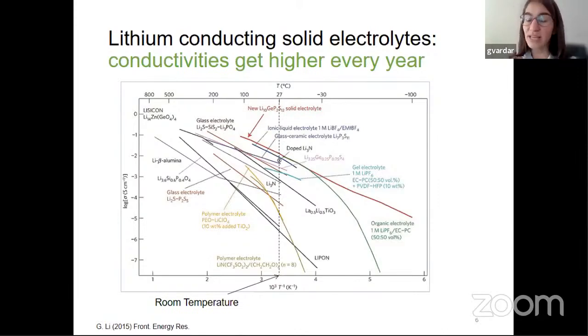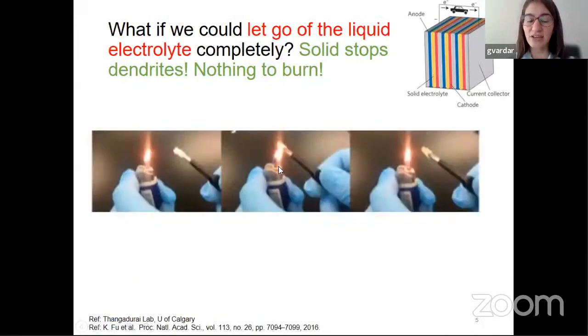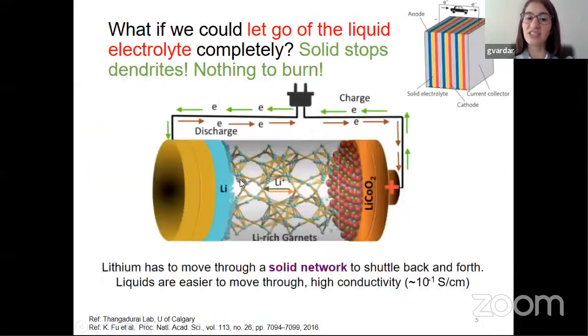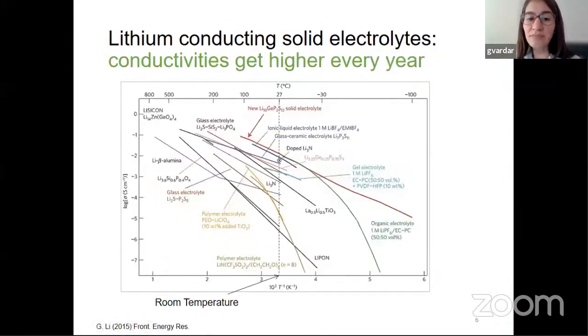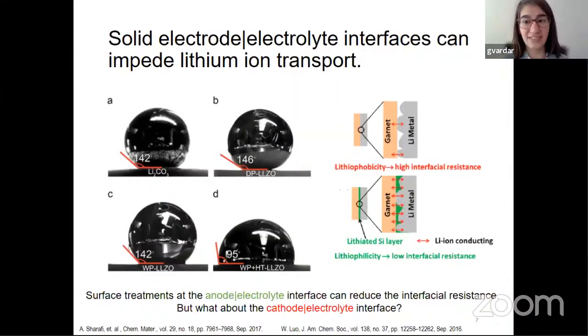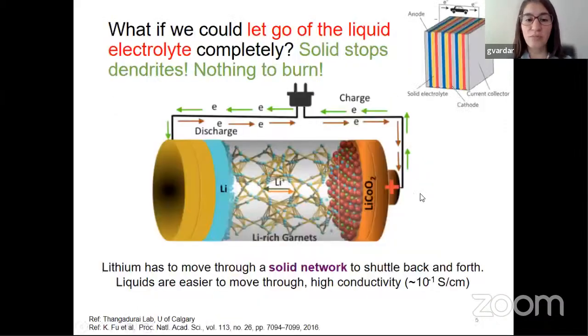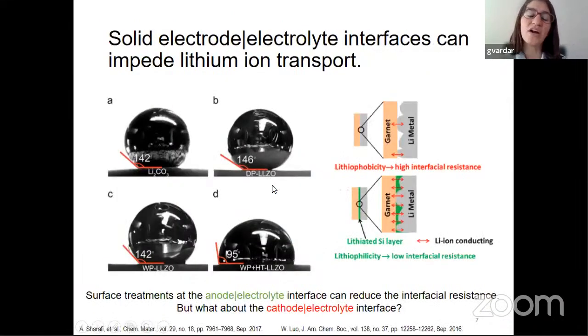So we have that. We have solid electrolytes. They don't catch fire. They can shuttle lithium back and forth at really high speeds. But then the problem becomes the interfaces. So here in this battery, you have this interface between the lithium electrolyte, this solid, and this cathode, and then you have the interface between the lithium and this other solid electrolyte. So these interfaces are basically what are the most problematic.